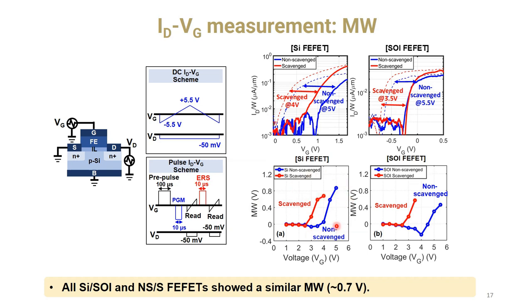And the same trend happened in the SOI FET. The SOI FET also has a maximum memory window around 0.7 volt, and a much lower voltage is required for the scavenging device. So the same trend happened in both the silicon and SOI FET for the memory window measurement.